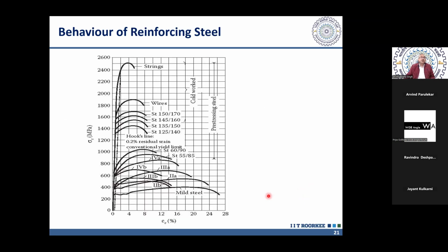So I will show you the behavior of different types of reinforcing steel. So mild steel, which we are not using anymore. This bottommost curve is for mild steel. The yield strength is roughly 250 megapascal. And we have a yield plateau. Then there is a strain hardening, and the ultimate strain is more than 25%. You can see here, this is in percent, more than 0.25. And in case of concrete, even after confinement, we were able to get 0.02. So that is 2%. So much less than what we are getting here.